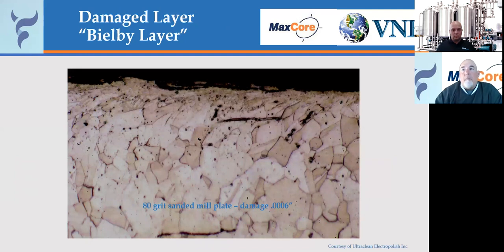This is a little higher magnification showing an 80 grit sanded mill plate and the damaged surface. You can see the striations along the top and the folded over metal, and you can see the damaged layer going down into this particular surface, all the way down into these areas, down into these grain boundaries here.